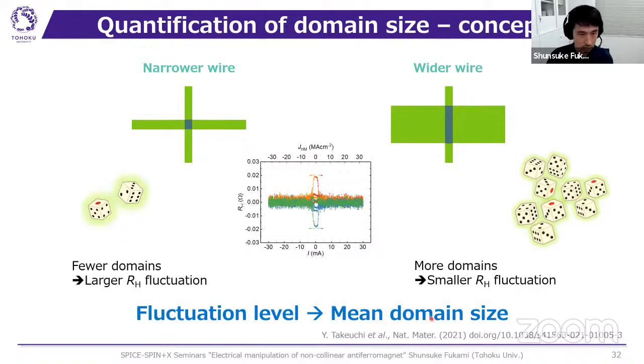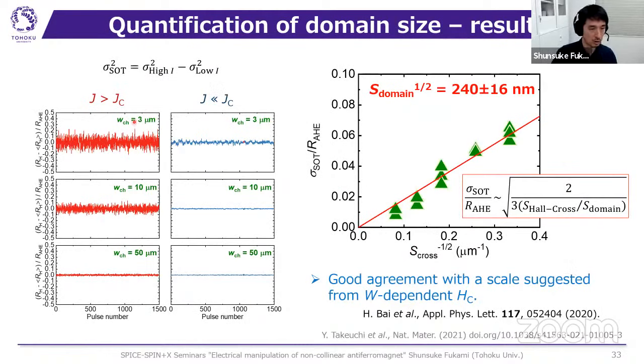So we did this experiment. We changed the channel width from 3 micrometers to 50 micrometers, and we observed the fluctuation level for each device. And as expected, the fluctuation level decreases with increasing channel width. And we have to take care here that the fluctuation comes from the fluctuation of the chiral spin structure plus the measurement error. So we have to subtract the measurement error by these equations and determine the fluctuation level owing to the spin orbit torque.